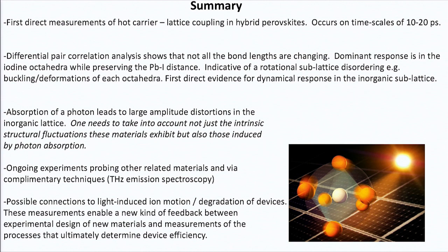And then in terms of the future, it hasn't escaped our attention that the iodine atoms in these prototypical perovskites are oftentimes the key mobile species that in the end determine the eventual degradation mechanisms and the lifetimes of these materials. So we think that in some sense we're capturing the first steps in these ionic hopping events occurring on picosecond timescales.